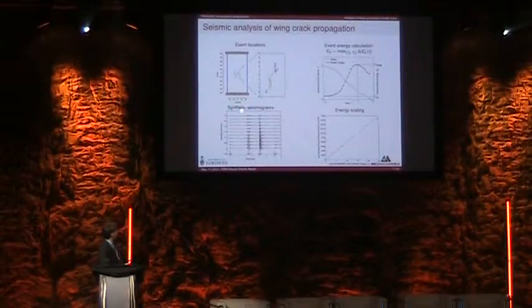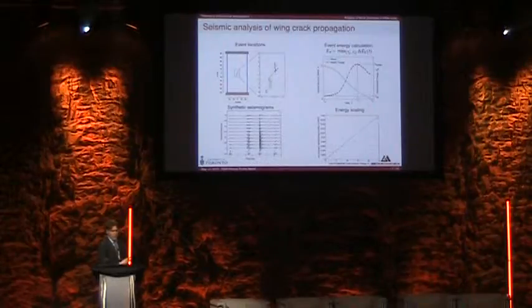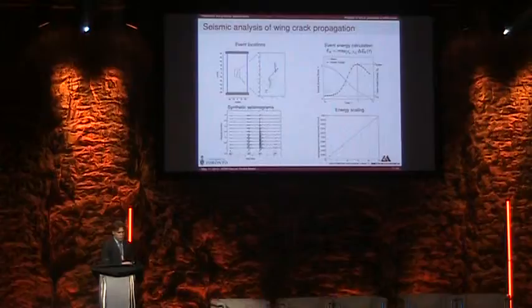At the same time, we are also recording the particle velocity on the side of the specimen, as you would do in the laboratory. So you can see we can record a synthetic seismogram. As fractures nucleate and propagate, the elastic energy that is stored in the rock is released in the form of seismic waves. We were actually able to use that information to locate back the source of the event. That way we validate the approach also from a dynamic point of view.